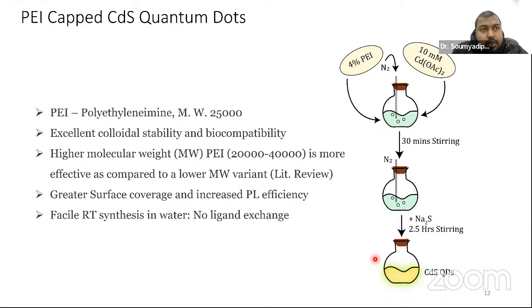What is our idea? The objective of our work was synthesizing water-soluble quantum dots. You can synthesize water-soluble quantum dots in two ways. Number one is to synthesize quantum dots in oil medium and then transfer them to the water phase by ligand transfer, or synthesize the quantum dots directly in water. The first one has a major problem: there's a loss of a considerable amount of quantum dots, because water deactivates them, because ligand exchange is not 100%. It cannot be 100%, and there is a quantum yield loss as well.